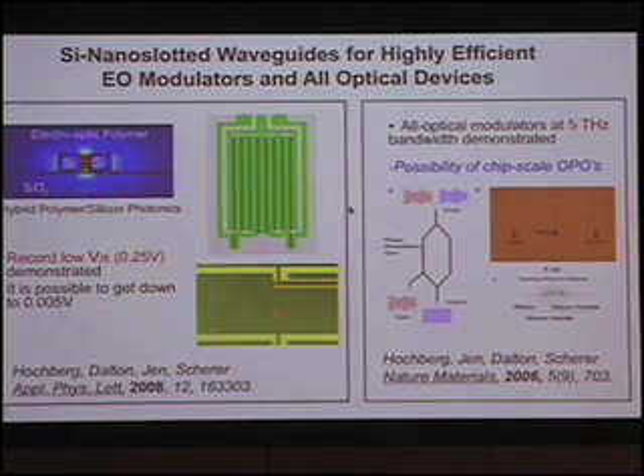Because of the continuity of the dielectric, the field of the silicon guiding mode can concentrate in this nano gap. When you put the nonlinear optical material inside, you can significantly improve the polarization. So this allows you to get a device with a very low voltage.